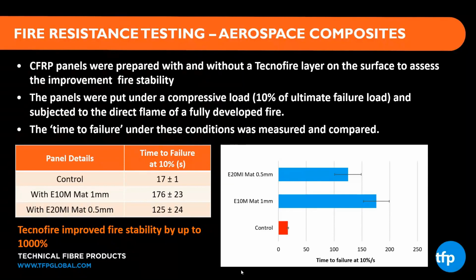If we look at the impact of incorporating the 0.5 millimeter layer of E20M, you can see that time to failure has been increased to 125 seconds. And through incorporation of the 1 millimeter E10M mat, that's been further increased to 176 seconds. So the Tecnofire has improved the fire stability, and fire stability really is an interchangeable term with fire resistance, by up to 1,000%. And hopefully from the description that Scott gave about how Tecnofire works, about the way that when the material, the veil, hits its activation temperature and swells or intumesces to form that stable insulating char that's protecting the backing laminate, you can conceptualize how that stable char is insulating, protecting the backing laminate, and allowing it to survive, allowing it to retain its mechanical properties, its compressive strength for a longer period of time.